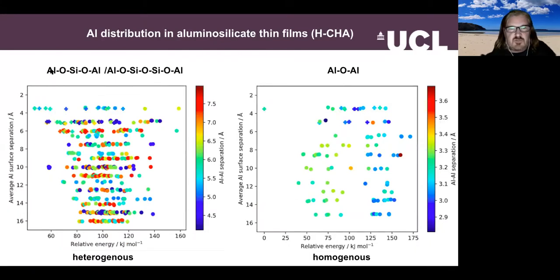This is the final results slide, and this is a kind of complex story that I just want to try and boil down. The vertical axis here shows the distance of the aluminium separation from the surface, the distance between the aluminium and the surface layer. So this is the external surface, and these are interior layers within the crystal. This is now actually a different composition to the sodium material that I showed you a while back. So this is actually proton compensated. This is one particular material called chabazite.